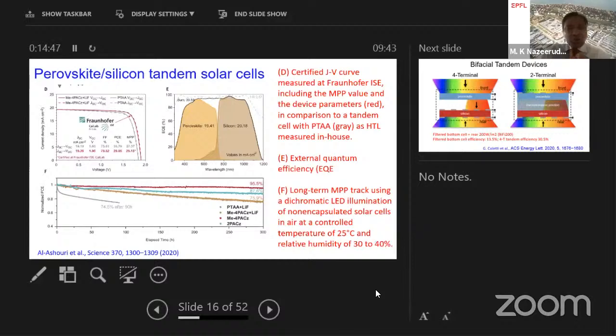Now, the next slide shows you the certified power conversion efficiency of this tandem configuration, which is 29.15%, certified at the Fraunhofer Institute. If you look at the E panel, it shows the EQE data of the perovskite solar cell and, at the same time, the silicon solar cell. If you compare the short circuit current, it is 19.4 coming from the perovskite solar cell, and the silicon solar cell gives 20 milliamp short circuit current. Because the currents are matching, it's a current-matched tandem configuration.